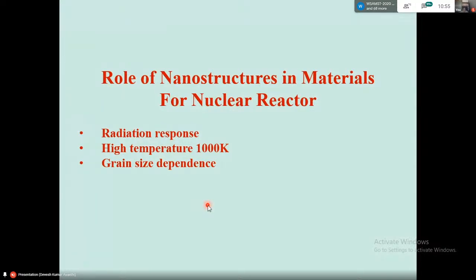In nuclear reactors, a lot of structural materials are used, and they should remain stable under radiation. In the radiation environment of a reactor, you have fission fragments, a lot of alpha particles, neutrons, and so on. But the temperature goes as high as 1000 K. The reactor temperature is 1000 K, and so we wanted to study the stability of these materials as a function of grain size, going into the nano size.